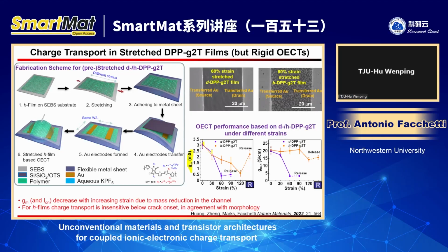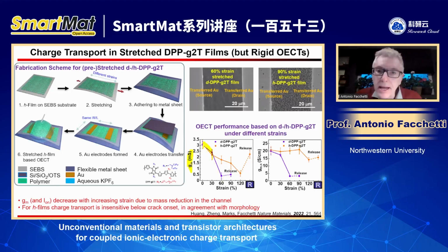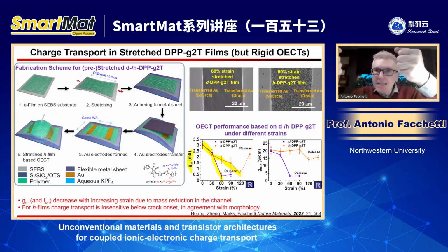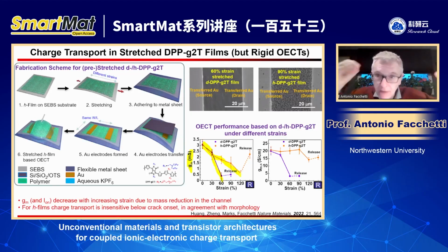So here the current is decreasing for the dense film, also for the honeycomb film. And this makes complete sense. The reason is that we have the same W/L, but we stretch the film, the semiconductor, so there is less mass between the source and drain. Less mass, and OECT is bulk charge transport, so you have less current. So the current must decrease when you stretch.